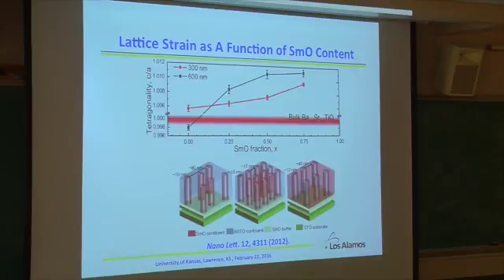When you do that, for example, here is barium strontium titanate. Look at this single phase material, and we go to like 300 nanometer or 600 nanometer. We look at the tetragonality. As you see over here, when you put more metal oxide, depending on ratio, you can really change the tetragonality. Basically, you keep this material as ferroelectric.